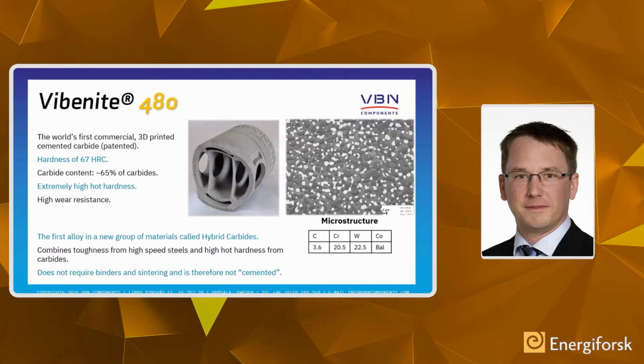Then we can reach a hardness of 67 Rockwells and a very, very high amount of carbides, which you can see here on the microstructure picture. And the basic major idea with this alloy was to close the gap between high-speed steel and cemented carbides, so that you get much better heat resistance, hot hardness, and still toughness that is very good for your applications. And typically tooling is one of the biggest areas, but of course you can use it in any kind of applications where you need both heat resistance and wear resistance.